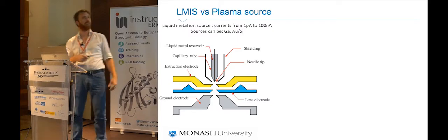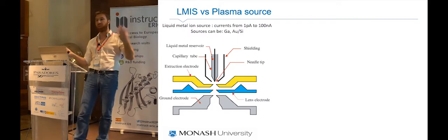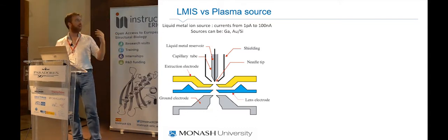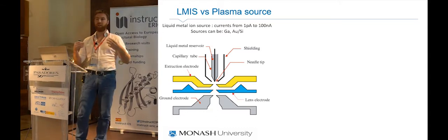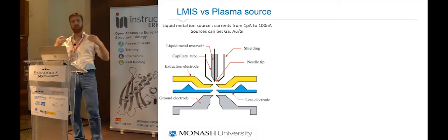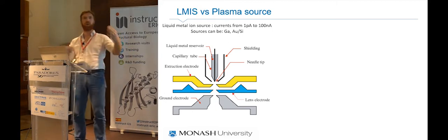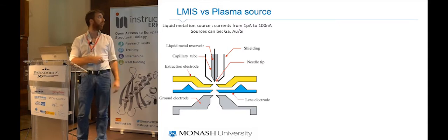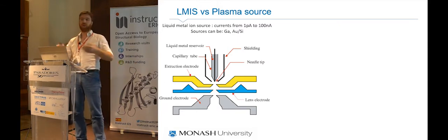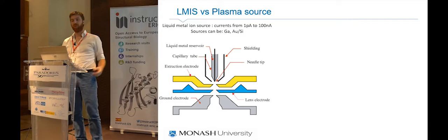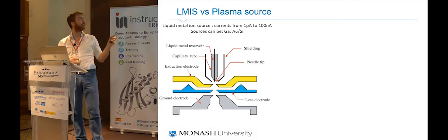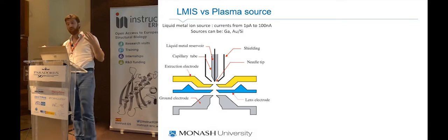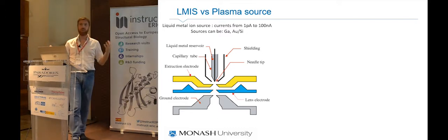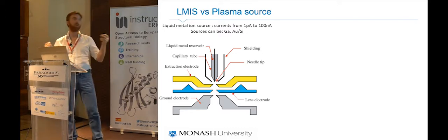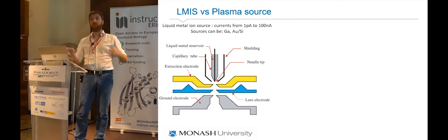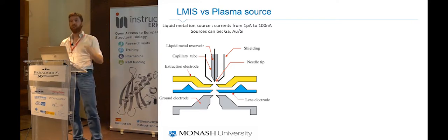This is the schematic. You have a tungsten filament which is coated with a liquid metal, could be gallium, could be gold, doesn't matter. You apply a very strong electrical field, and ions will be extracted from the tip of the filament, accelerated and focused onto your sample. What's very important here is that you can have very high resolution. Your tip defines the source size, which means you'll be able to have a spot size down to a couple of nanometers.